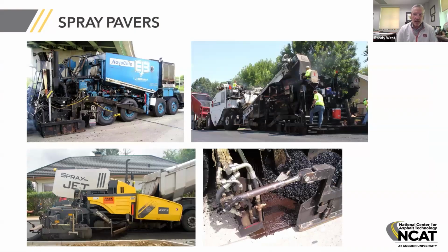Another way to make sure you don't get your tack picked up by your paving equipment is to apply it with a spray paver. So the original spray pavers were the McConnaughay kind of paver used for a Novachip application. And on each of these, you have a large tank that has the capacity to hold the emulsion, and that tack coat is applied. In the bottom right picture, there are spray bars right there in front of the auger box on the paver. So that patent expired, I don't know, maybe 5 to 10 years ago, and now Astec has a spray paver and Vögele has a spray paver. So you can apply that tack material right in front of the mix, and that's what you see on the surface in the bottom right.